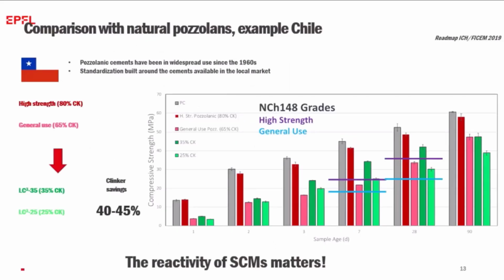And this is a nice comparison based on cements in Chile, which have used natural uncalcined pozzolans since the 1960s. They have 2 cements on the market, one with 20% replacement, one with 35% replacement. Now if you go from a natural uncalcined pozzolan to calcined clay, you can match that performance at much, much lower clinker contents. You can match the performance of the high-strength blend, 80% clinker, with only 35% clinker, and the general use one with only 25% clinker.